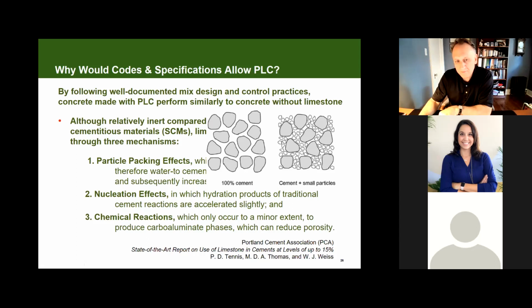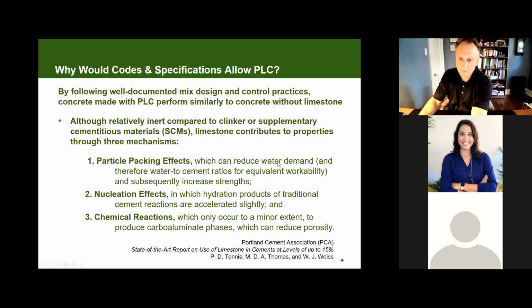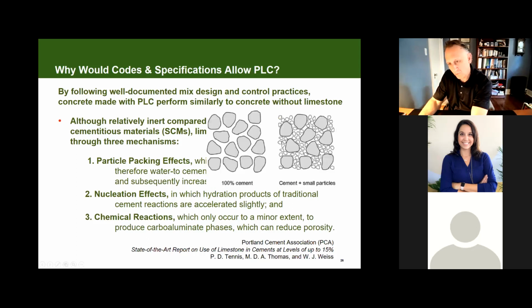And so what happens there is, you're creating almost like a better skeletal system of the overall matrix, if that makes sense. So the skeletal system of the matrix is becoming denser, and with this we see some improvements in the cement. For example, you can have reduced water demand, and therefore lower water to cement ratios for equivalent workability and subsequently increased strengths. So the idea is this particle packing effect.